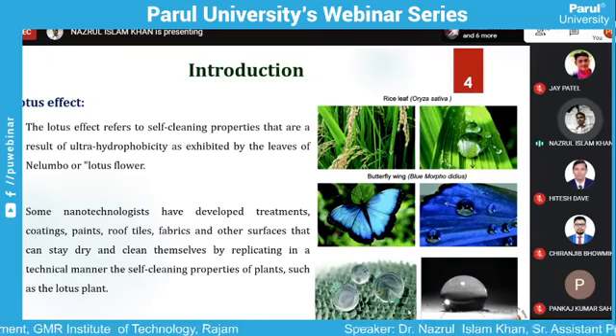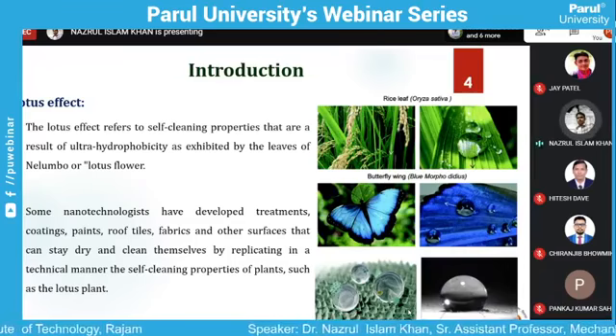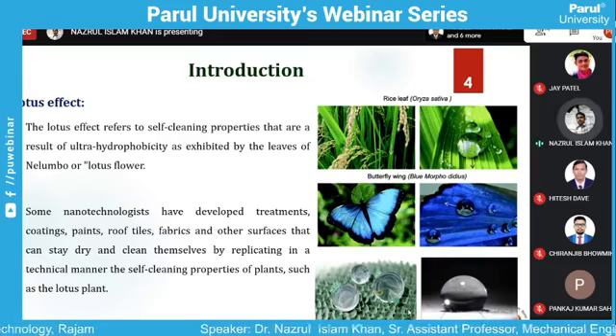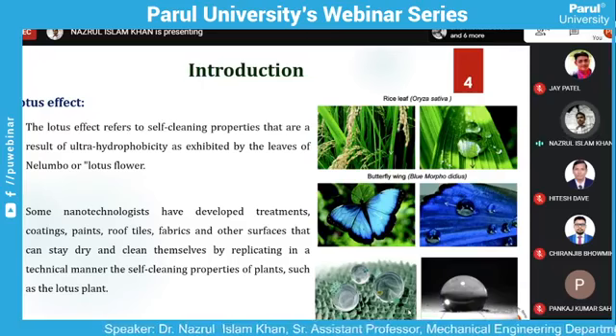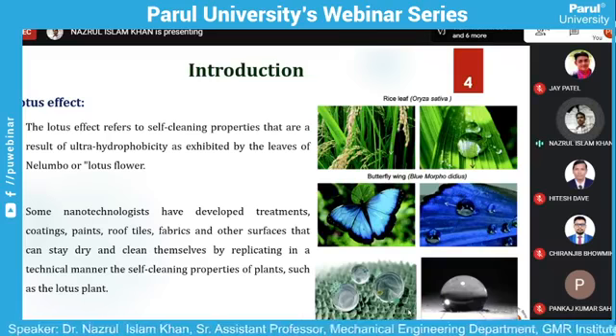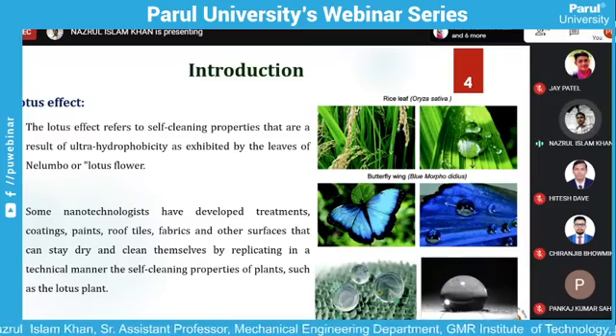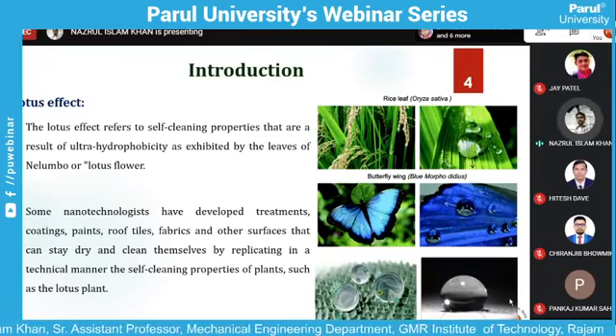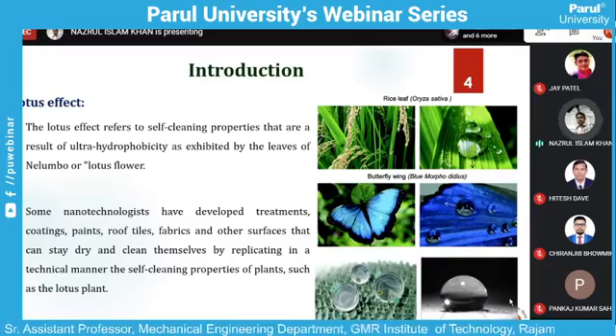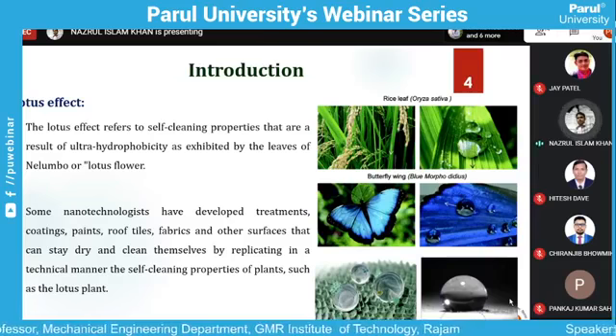If you assume any particle inside the water, it is surrounded by only water particles, so the force acting there is cohesive force. Now what about a particle on the surface? On the surface, since it is the attractive force between the surrounding and two dissimilar substances, an adhesive force takes place. Due to this combination of adhesive and cohesive forces, there is high surface tension, and the water droplet takes a spherical shape. Whenever it comes in contact with any dust particle present on the surface of the leaf, it carries that dust particle away, but it will not wet the surface.